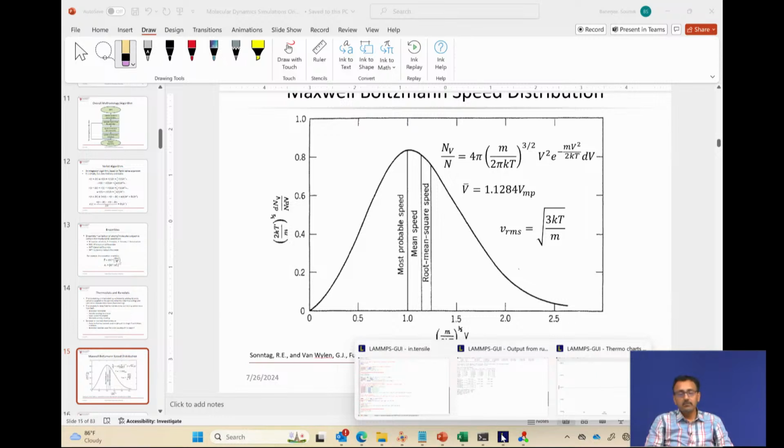Now, you might be tempted to say, well, let me use a thermostat to check the temperature every step or every 5 steps. There's a problem with that. You're shocking the system if you're continuously scaling its velocity, through that perturbation. So you want a very weak thermostat, by which we mean the relaxation time of the thermostat is at least every 1,000 steps, if not every 10,000 steps.